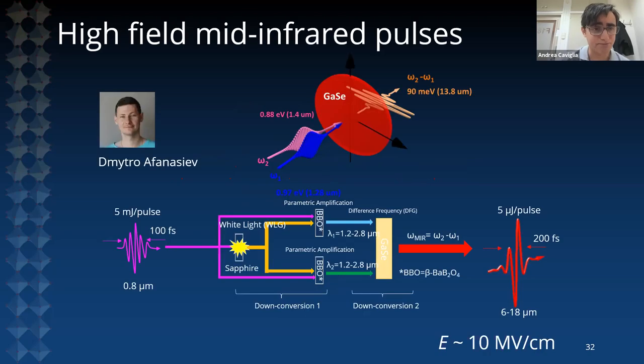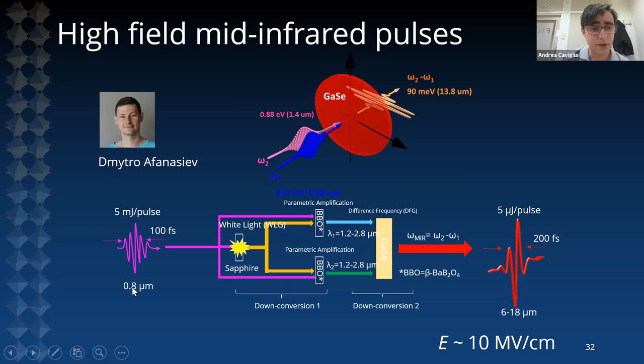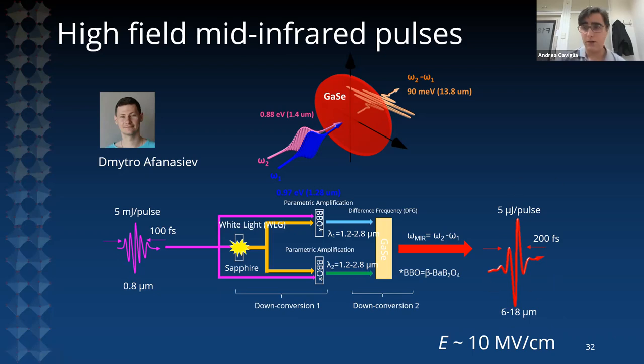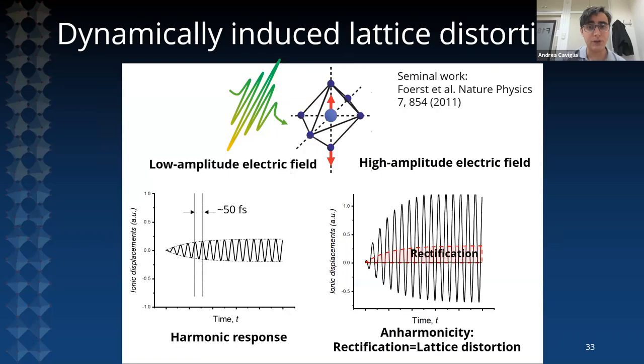We need something stronger. In our lab, Dima Afanasyev has been building a very nice powerful mid-infrared laser source. By taking the output of a femtosecond laser and converting it with a series of nonlinear optical effects, he is able to produce pulses of mid-infrared light tuned in resonance with phonon modes, carrying electric fields of the order of 10 MV/cm. With this type of pulses you can induce a lattice displacement of a percent of the lattice spacing and induce relevant changes in the properties of materials.